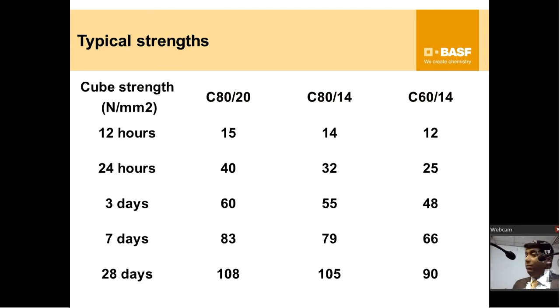Strength achieved: 12 MPa was what was required at 12 hours, we had 15, 14 and 12. At 24 hours, 3 days, 7 days, 28 days, 108 for a C80 grade concrete. So you end up getting very high strength as well. This was the strength being achieved on M80, C80 with 108 and 105, tested at 28 days. Crushing, yeah.